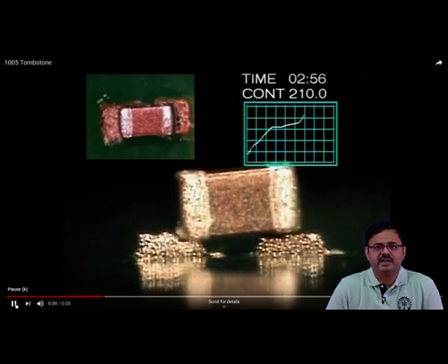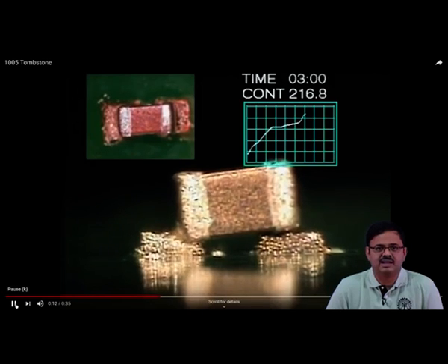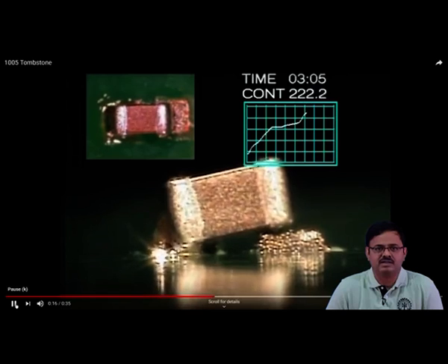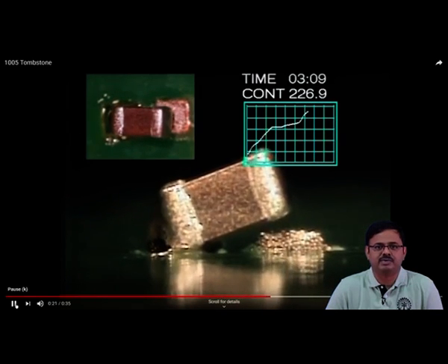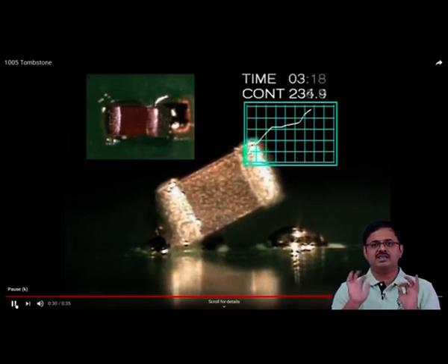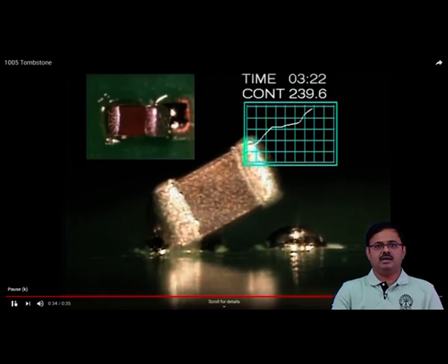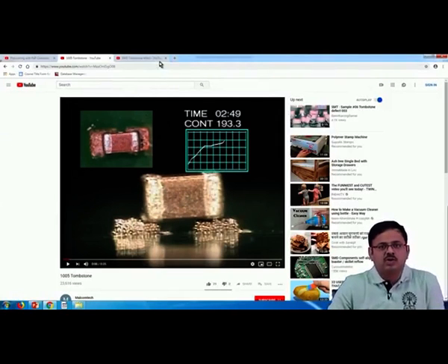There is unequal wetting, and you see along with time one side, the left side is getting wetted, the right side not so much, and you see this detachment, right, it has lifted up. And now this one started to wet, but by that time the detachment had already happened and the final configuration is a defective package. Okay. All right. So, let us look further.